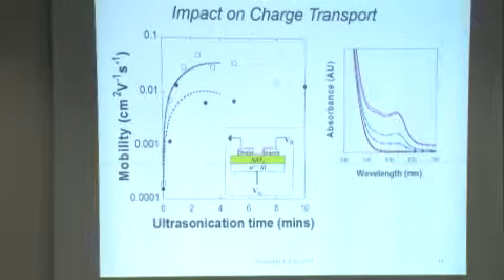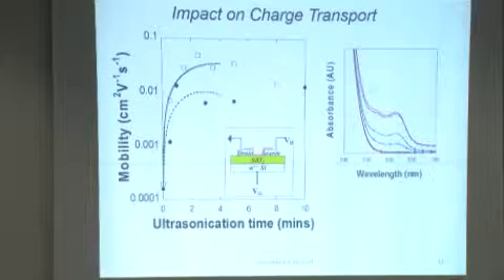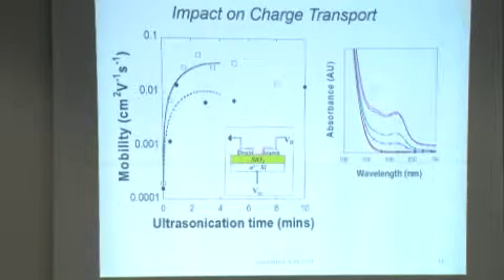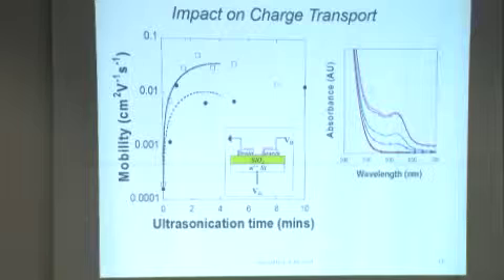Rather than better mobility, as we sonicated, we got better up to a point, and then the change in mobility basically saturated. So we could improve the charge transport characteristics, but then we couldn't go any further. All right, and these are the mobility versus sonication time results, and these are the absorption spectra, so you can see what's happening to those bands.